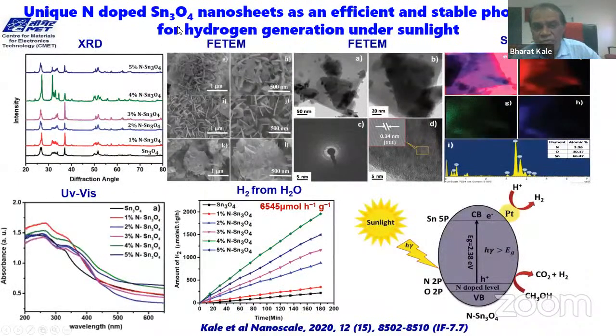Then Sn3O4. Sn3O4 is a good photocatalyst, and it's again in the UV region. We thought that we could dope with nitrogen and see whether we can make the Sn3O4 porous and have good photocatalytic activity. And we found here, you see, it's a plate-like Sn3O4. When we dope with nitrogen, we get highly crystalline nanoplates, which helps a lot for enhancing the hydrogen evolution.